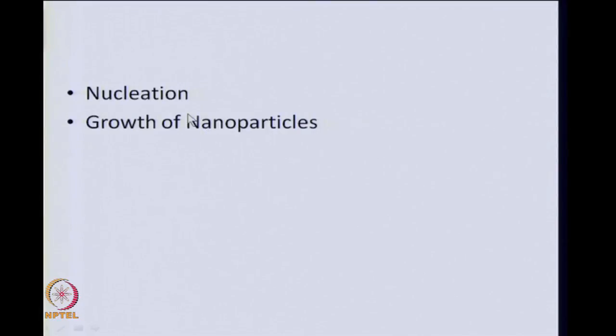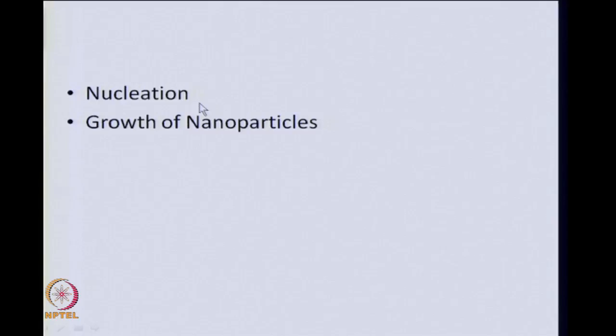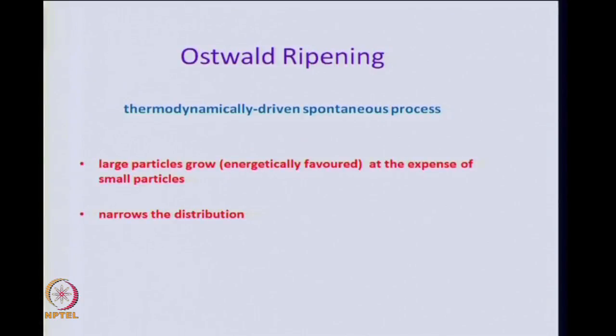You have first nucleation, and then these nuclei grow to form the nanocrystals or nanoparticles. And the important thing is that how to control the size of the nanoparticles depends on how you control the growth of these nanoparticles. So, to understand the methodology of controlling the size of nanoparticles, we have to understand the thermodynamics and kinetics of these two processes, which are nucleation and growth of these nanocrystalline materials. So, one of the mechanisms by which these nanocrystals form and grow is what is called the Ostwald ripening